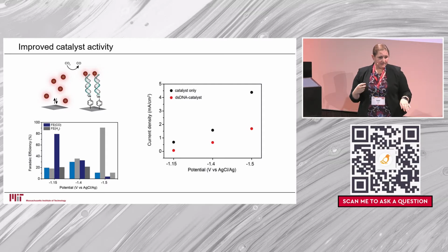And importantly, on the bottom here, what we see is with our optimized system, we get nearly 80% Faradaic efficiency. So that means for every electron we're putting in, we get 0.8 molecules of CO. That is unprecedented. The majority of these porphyrin catalysts in solution look like the rest of this graph. You either get significant amounts of hydrogen production, which is not what we want, or you get nearly no conversion at all, with really low Faradaic efficiency. So being able to get 80% conversion by just simply sticking this to an electrode using a really easy molecule to use is really unprecedented.